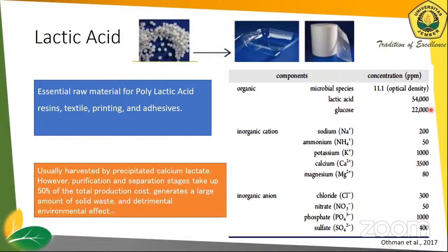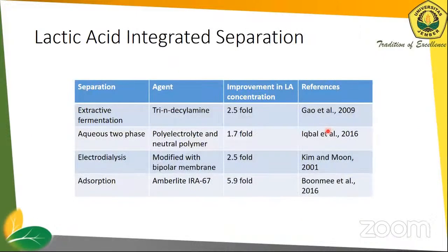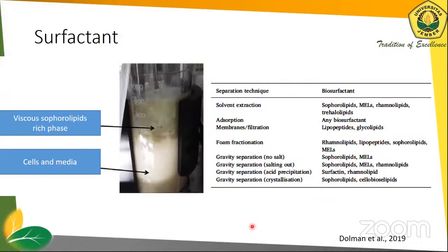In the media of lactic acid, the concentration reached around 54,000 ppm. It is inhibiting the lactic acid production by the bacteria. This is some integrated separation for lactic acid. There are extractive fermentation, aqueous two-phase separation, electrodialysis, and adsorption. And also there is the surfactant process by fermentation, such as lipids.